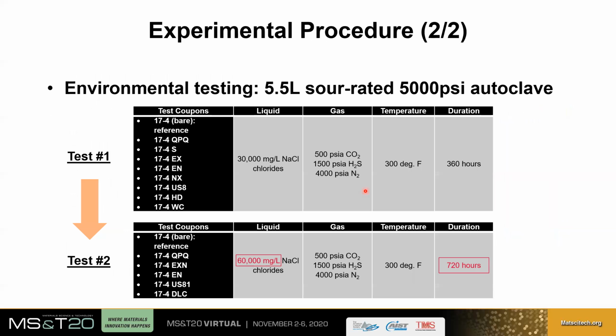All right, so here's a description of the environment. So 2 tests were conducted. The second one complements the first one. All tests were conducted by an external laboratory. They used essentially sour-rated autoclaves, 5,000 psi. So we can see our coupons were subject to these 2 test runs. The environment for test number 2 is more aggressive than test number 1, simply because we increased the chlorides and we also made the test longer, to 720 hours or 1 month.